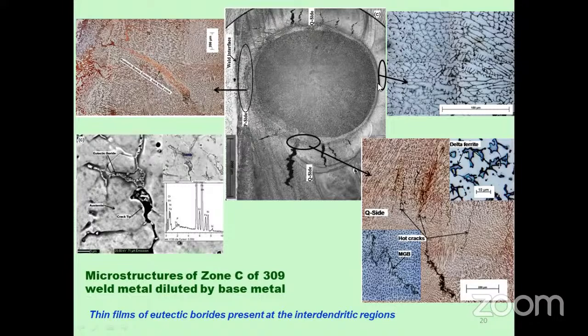And very far away from this region, on the other side, closer to the weld center, we see that there are no borides and there is only austenite and delta ferrite. That is, this 309 electrode, when it solidifies, solidifies in a ferritic mode. That is, the first phase that is formed is the ferrite phase, and it has a duplex microstructure, that is, delta ferrite is there in the austenite matrix. So in this region, because there are no borides, there is no cracking. Here there are borides, and sufficient borides are there to backfill the cracks.